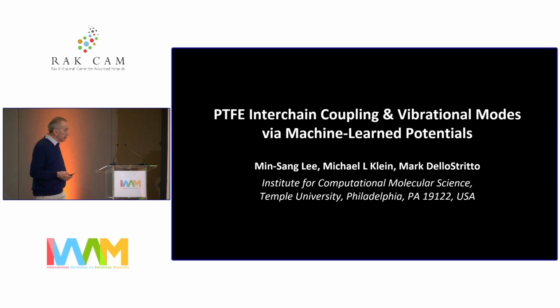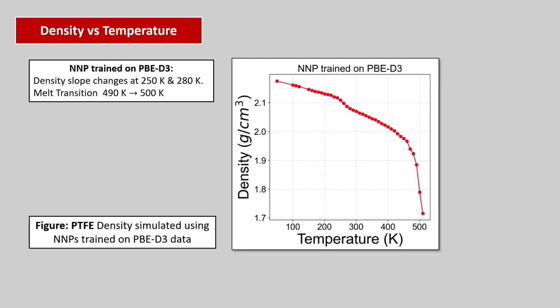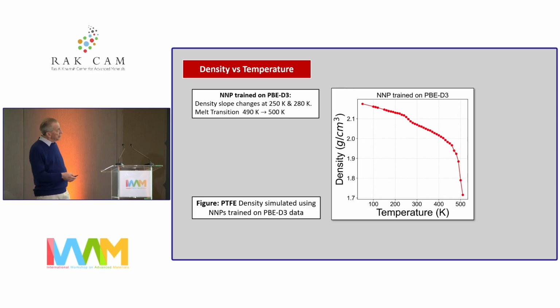So I think I've used up my time pretty much. I haven't shown you what we've actually done, although we have 2 papers at the moment going through review process in Journal of Chemical Physics. They'll be out soon. We've tried all sorts of methods, and we found that you have to include van der Waals forces, not surprisingly. And the most primitive model of density functional theory, as I put here, seems to be the one that is doing the best. It has a phase transition in the right temperature range. It seems to show the onset of a melting behavior roughly in the right place.